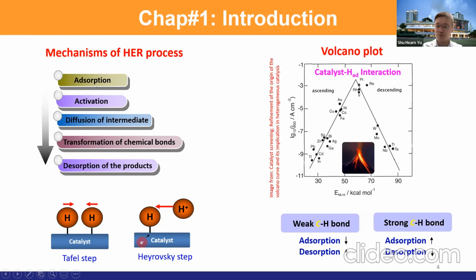reaction. And then we have the very famous volcano plot. So basically, we need to find a catalyst that has a moderate interaction with the hydrogen. If we have a very strong interaction of the catalyst with the hydrogen, then the adsorption process is favorable. However, the desorption process will be unfavorable. So the overall reaction will be sluggish because the desorption process will be the rate limiting step.